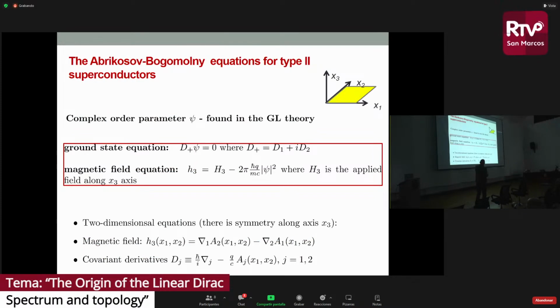So these equations are what I call the Abrikosov-Bogomolny equations, okay? They describe the order parameter here, where the D are these derivatives in the plane, okay? And a second equation that gives you the local field. Everything is translationally symmetric along an axis. Okay, so these are the fundamental equations that I'm talking about, the most fundamental structure able to describe vortices. Many of you have solved the Ginzburg-Landau theory, have thought about vortices and never heard of these equations. You don't have to, but when you go and see what's the most fundamental mathematical structure behind vortices, which are topologically stable structures, it is exactly these equations.